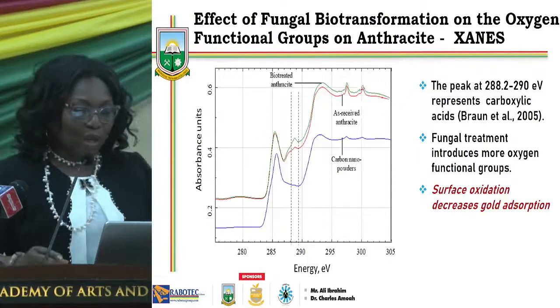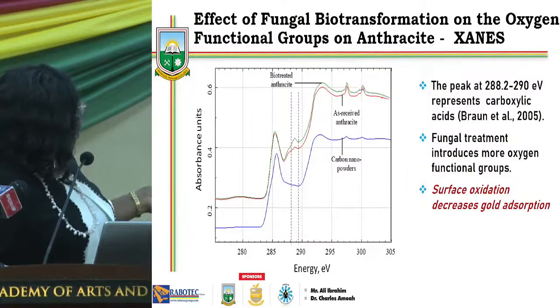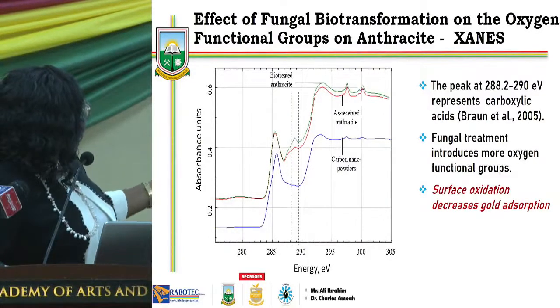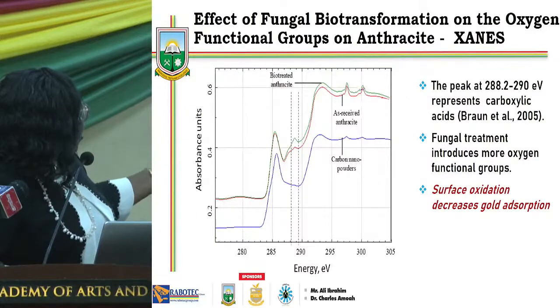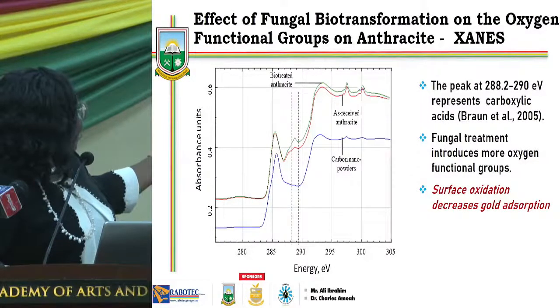Then this one shows oxygen on the surface of the carbon. From this diagram, the message is that on this side, what we have here is carboxylic acid. The green line is showing the biotreated anthracite, and the red line is the as received.